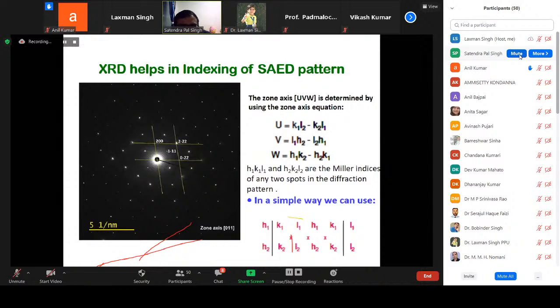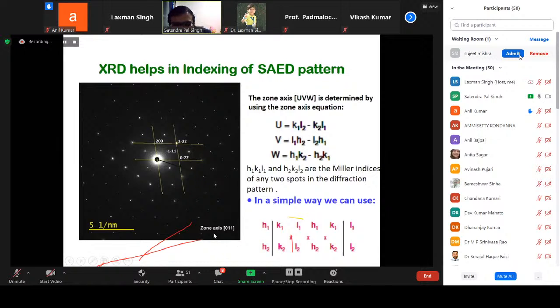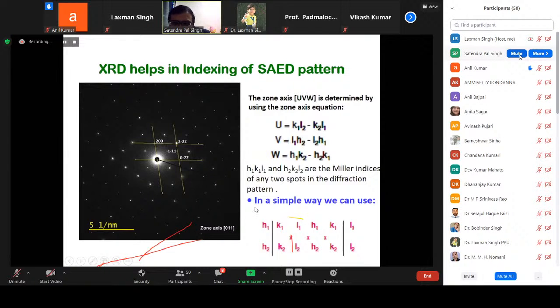Once you know the HKL values for each and every diffraction spot, you will be able to obtain the zone axis. What is the zone axis? The zone axis here is 0, 1, 1. How do I get this zone axis? We can get the zone axis by using a relationship.